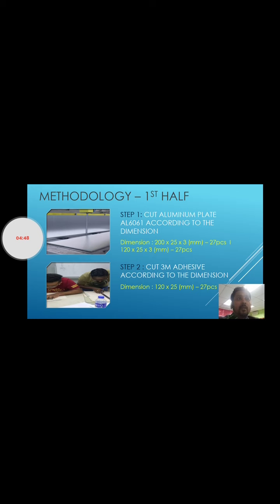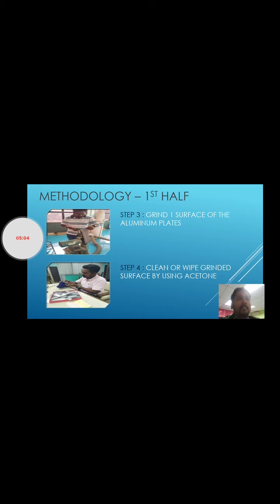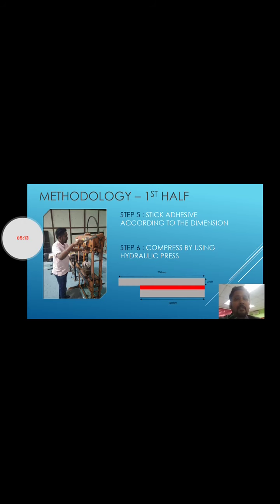Okay, this is the methodology for the first half. Step 1, cut aluminium plate AL6061 according to the dimension. Step 2, cut 3M adhesive according to the dimension. Step 3, grind one surface of the aluminium plates. Step 4, clean or wipe the ground surface using acetone. Step 5, stick adhesive according to the dimension. Step 6, compress using a hydraulic press.